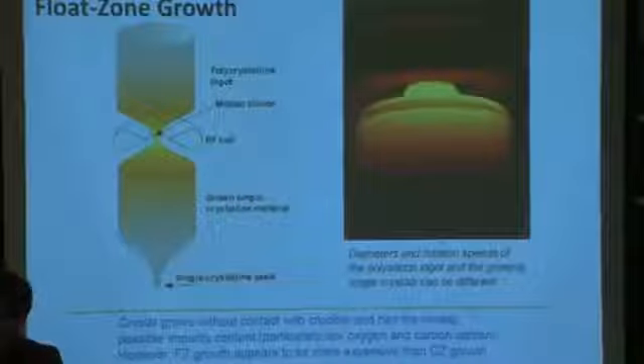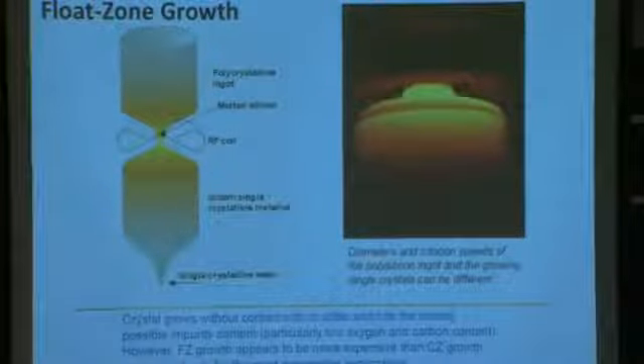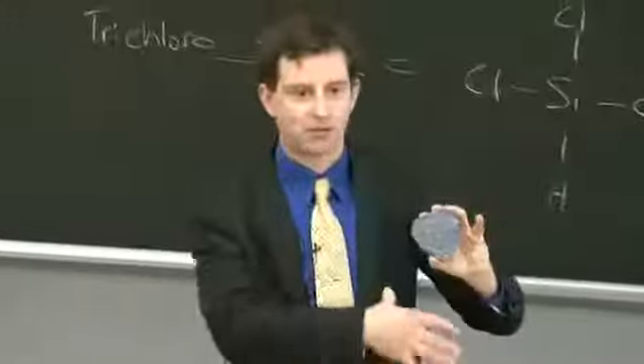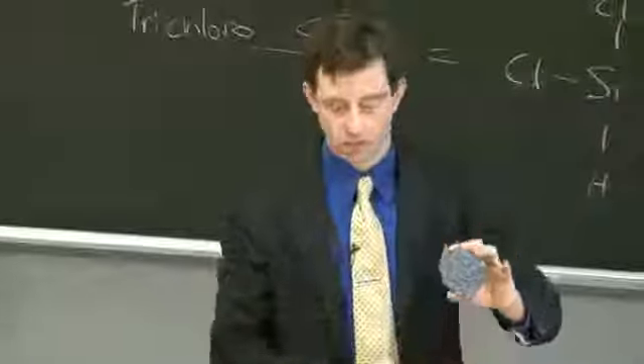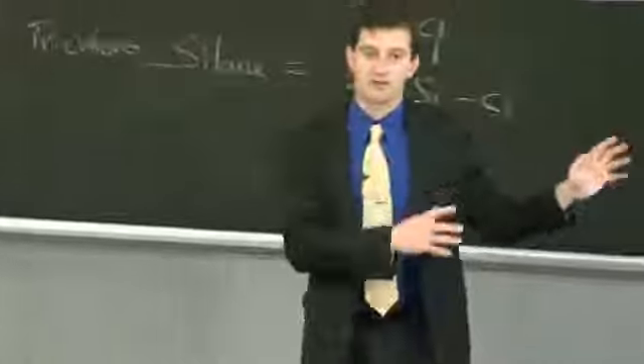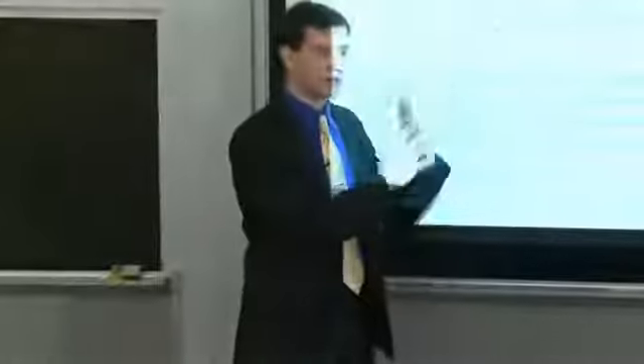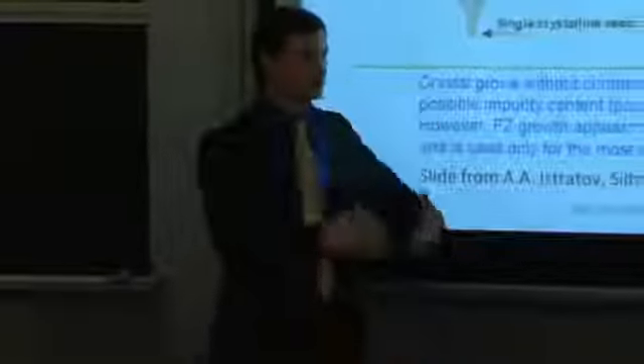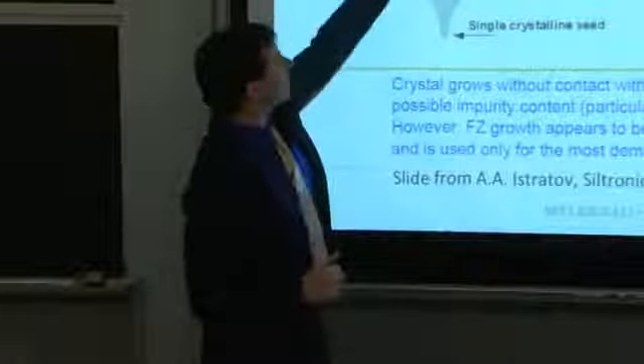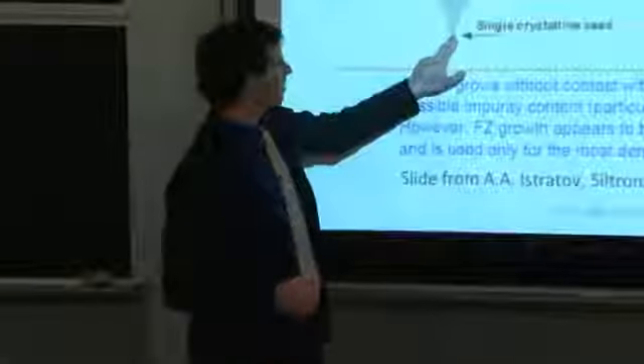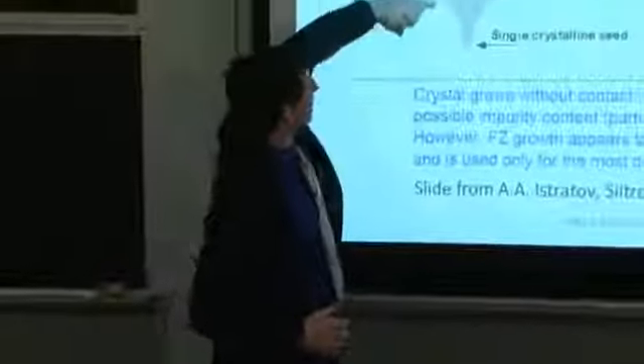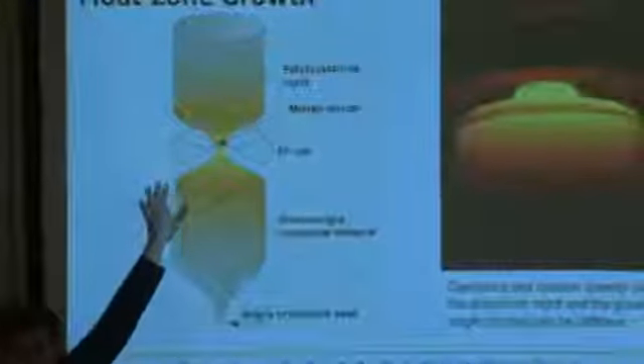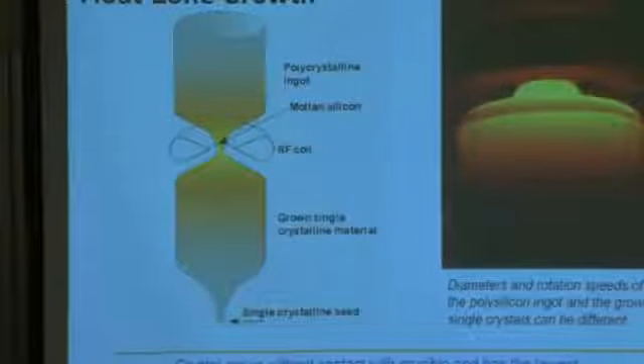And you start with the polycrystalline rod coming from the Siemens process. In that case, this rough corrugated material right here won't do, right? This is too rough for that RF coil to pass over and be a consistent distance away. In the case of float zone growth, you actually have to modify your polysilicon production process. You have to modify the Siemens process so that you get a nice, smooth rod, which you can then pass the RF coil next to and melt. And you again start with a seed at the bottom. Your RF coil starts down here, and then the RF coil moves through the material, almost like a comb from the bottom to the top, converting the polysilicon into nice single crystalline material.